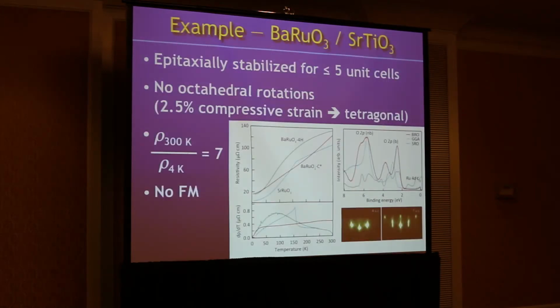And so here I'm showing some unpublished results, but basically using a substrate, I'm not saying this is by any means the best substrate, but if we want to stabilize this cubic polymorph, we're going to put it on top of this cubic perovskite substrate. And this is lattice mismatched by a huge amount. Okay. The other substrates I showed you a second ago weren't cubic, so they have their own rotations. But this one is cubic, so we have no octahedral rotations here. You can stabilize this for very thin films. Okay, so less than 5 unit cells, we've been able to stabilize this metastable polymorph, something that takes in bulk 180,000 atmospheres. You can do it in thin film form with the proper substrate.